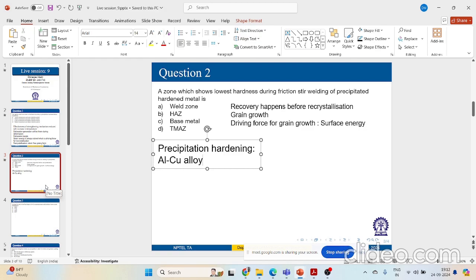So there are different precipitation strengthened base metals, right? If you see the aluminum series, there is the AA 2000 series. We denote it something like this. This is aluminum 2000 series, aluminum 6000 series, aluminum 7000 series. These are some of the precipitation hardened metals, and they can be developed either by fusion welding or solid state joining process if you are raising the temperature of your base metal high enough.